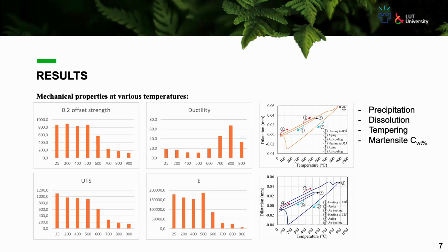The dilatometry results of this material from our previous studies show that this temperature range is the range that can cause precipitation and dissolution in the microstructure. However, a high number of carbide particles are not expected in the as-built version. So in this case, I think the tempering effect of the background martensite is a dominant factor, which also manifests itself in the decrease in ductility because of the presence of carbides, but it's still a low carbon steel. So the influence is not that significant, but it's still there.